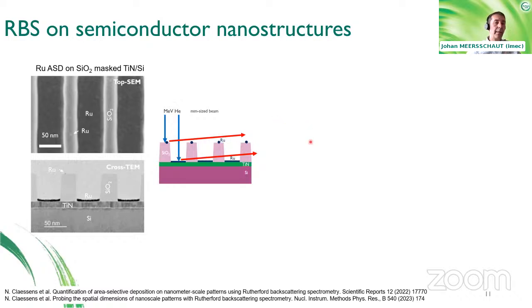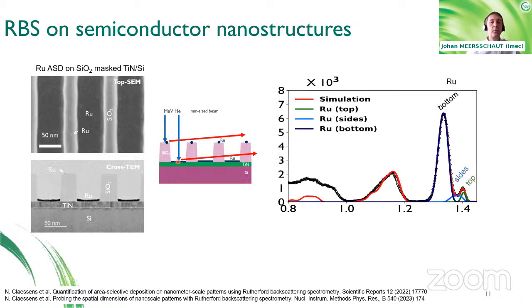We put the detector at a shallow exit angle, and we make use of the energy loss of the ions when they penetrate through the silicon oxide fins. You can understand that when particles are being scattered on the ruthenium on the top, then they will not lose excessive energy by going through the silicon oxide fins. On the other hand, when you scatter on the bottom of the samples, you will lose a certain amount of energy before you go to the detector. And this is exactly what we observe when we look at the energy spectrum for ruthenium on such a sample.